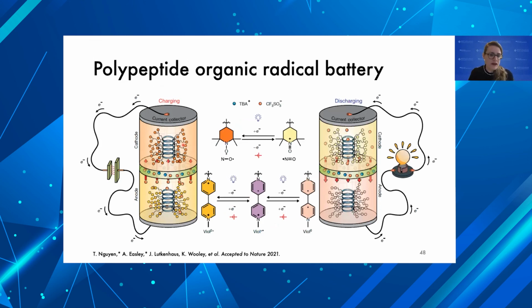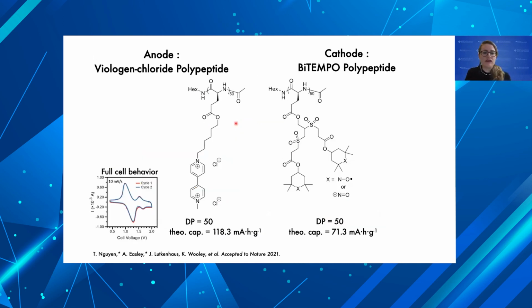So this is a schematic of the battery where we have the polypeptide cathode and anode. The cathode uses the TEMPO group hanging off the polypeptide backbone, which we've just talked about in this presentation. And for the anode, we use a viologen. This is the specific molecular structure of the molecules we have. And we've calculated the theoretical capacities of each of them. So in principle, they can have very high theoretical capacities of 118 and 71 milliamp hours per gram for the viologen and the TEMPO-containing polypeptides, respectively.